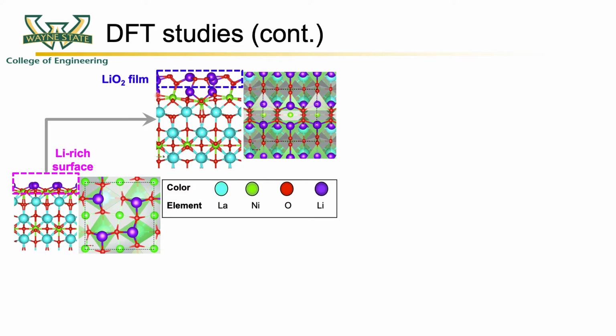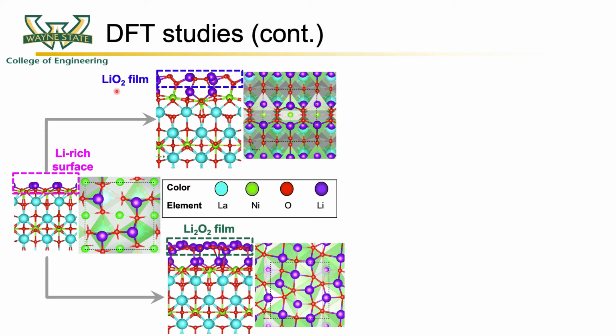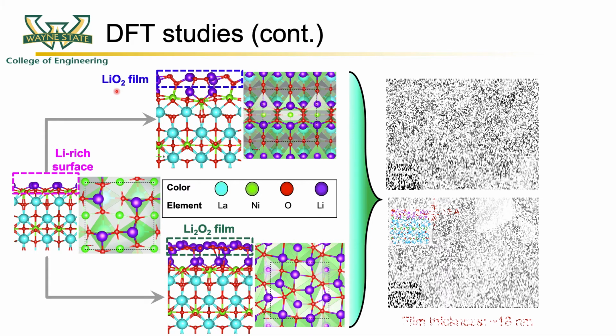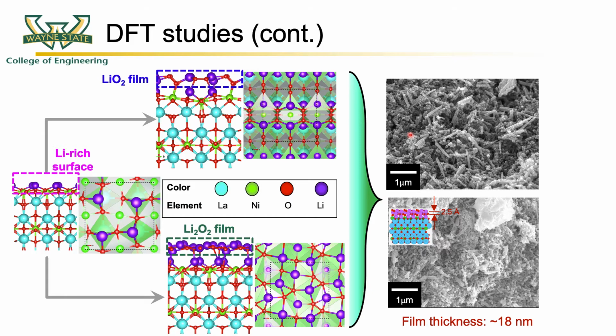This lithium-rich region then provides a template for the further growth of LiO2 and Li2O2-like species. This is consistent with our experimental studies where the SEM of the pristine and discharged electrode shows the formation of film-like species with a film thickness of roughly 18 nanometers.